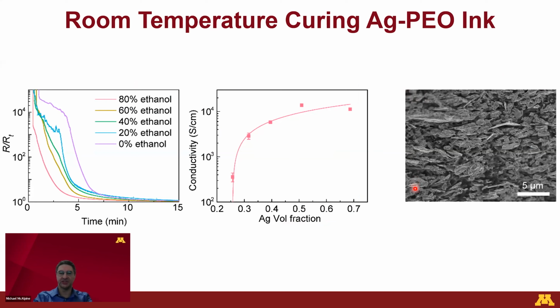And as you can see here, part of the magic of that happening is that there's silver flakes here, and the printing process actually shear aligns them so that they overlap with one another. And therefore, you have a nice overlap of the silver, creating a conducting pathway so that you don't have to do that additional sintering step, which would obviously damage the ink at temperatures that are too high.